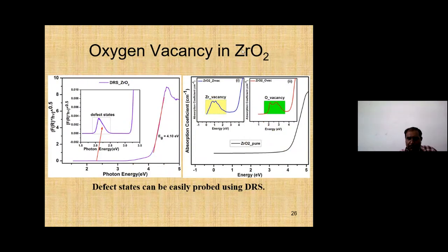In the case of zirconium oxide, what we have done is the following. We have produced the zirconium vacancy, we have also produced the oxygen vacancy, and if you see, the states due to oxygen vacancy are coming very close to 2.5 electron volt, and the states due to zirconium vacancy are coming very close to 1 electron volt.